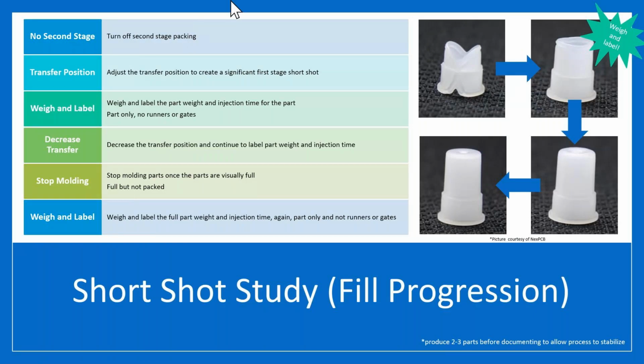So the short shot study lets us determine the appropriate volume to inject into the tool to hit that 95 to 98% so that we can transfer to pack. In order to do this, we're going to make sure that pack and hold is zeroed out or turned off. No pack and holding pressure, no pack and holding time. We're going to adjust our transfer position upwards so that we do in fact achieve a short shot.